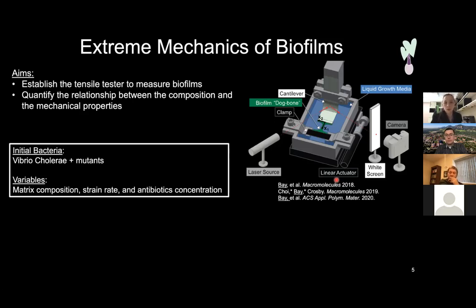So Howard Stone's group has shown that they can grow their agar, they can grow their films, and they were doing adhesion measurements, but they can do capillary peeling. So if they just lift them off the water, they take the film, they bring it into the water contact, and then they have a film on top of the liquid substrate. And so they've been able to show that you lose some of the adhesion protein. So that's an interesting thing.